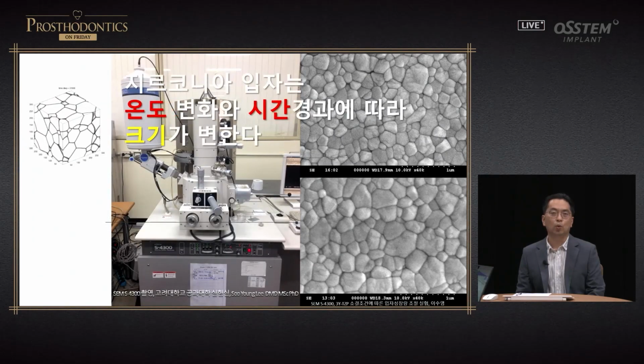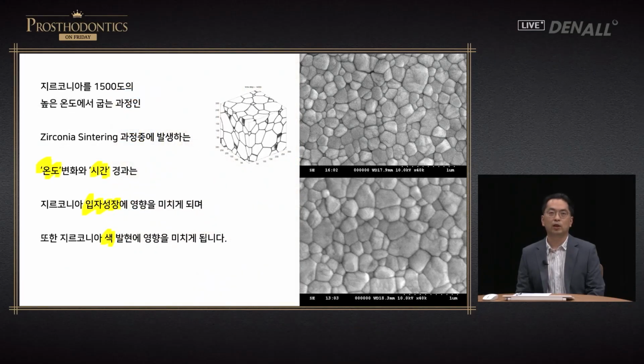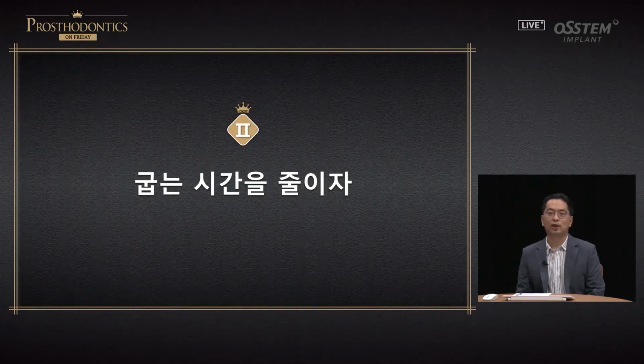The zirconia molecule size changes depending on temperature and time. Through these series of changes, the zirconia's optical properties as well as translucency are improved. 1,500 degrees in which zirconia is sintered is quite high. Sintering process occurs in this temperature. Through temperature and time, the molecule grows, and it also affects how the color is expressed. For one-day zirconia restoration, we need to reduce sintering time.